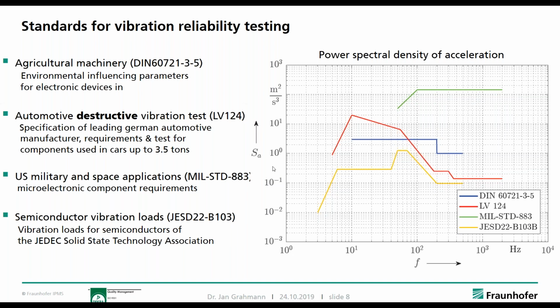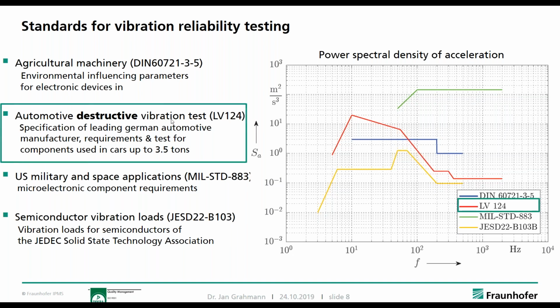So we used here an automotive destructive vibration test, primarily to see how it affects the scanner in operation. So it is basically a worst case that we use here in order to determine that characteristic. And you can see that this red line here has a quite high power spectral density between 3 and 100 hertz, and then drops down by 200 hertz and further to higher frequencies up to 2 kilohertz.